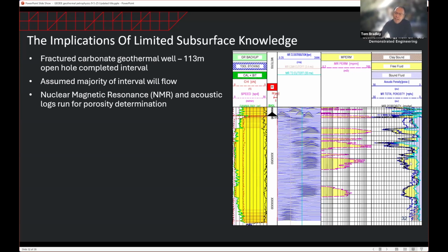What I have plotted over here is similar to what happened in an earlier slide, this distribution of porosity, with yellow shading indicating movable porosity, blue shading indicating irreducible porosity that will probably not move, and your brown dashed shading indicating your clay-bound porosity in the shale that will not move.